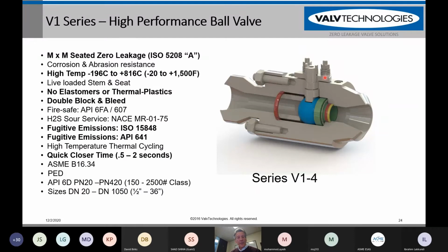This is our V series valve. You can see right here it has a number of Belleville washers on the bonnet area. It is a 1/4 turn valve. It's live loaded. It has 0 leakage. It's rated up to 1500 degrees Fahrenheit, or about 816 degrees Celsius. It does not utilize any thermoplastics or elastomeric seals. It is bidirectional and double block and bleed. It meets all industry standards for fire safe, and NACE for H2S service. It also meets all the industry standards for fugitive emissions, as all of our valves do. And because of the low porosity that we have on the contact between the tungsten carbide on the ball and seating areas, we're able to open and close our valves very, very quickly. All of our valves also are SIL 3 and SIL 4 certified.